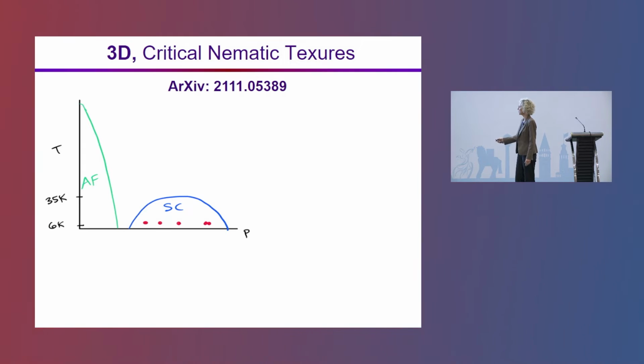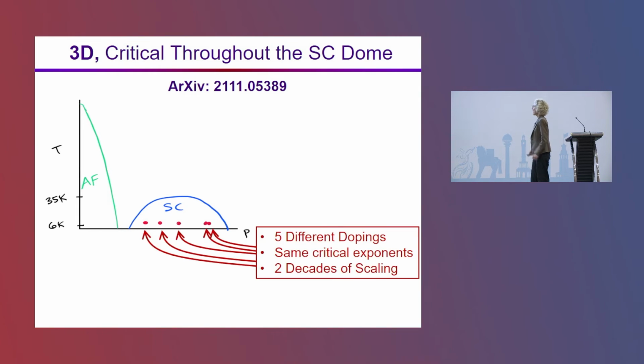What I showed you is inside the superconducting dome, the underdoped 32 Kelvin sample. But Jenny and Eric have samples that cover the entire doping range from underdoped to optimally doped to overdoped. We did this same analysis on 5 different dopings. We see the same critical exponents at every doping. That's consistent with critical behavior. As a function of parameters, the critical exponents should not shift. What should change is the correlation length, like we saw with the test tube demonstration. The correlation length grows to infinity at the critical point and then comes back away again.